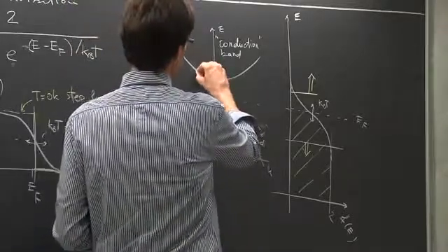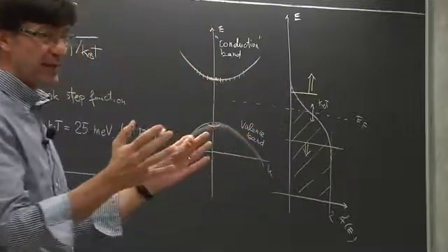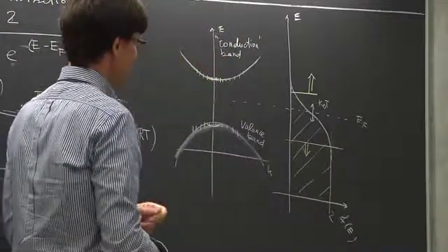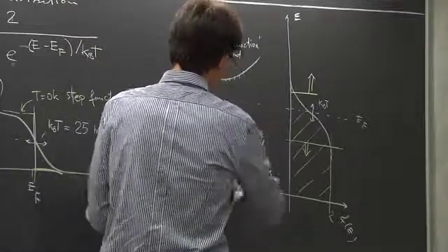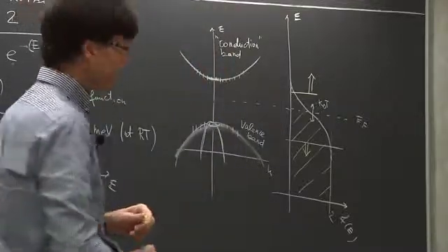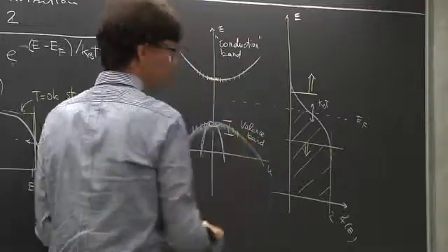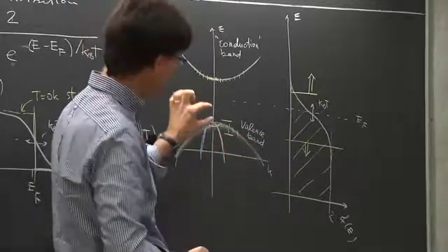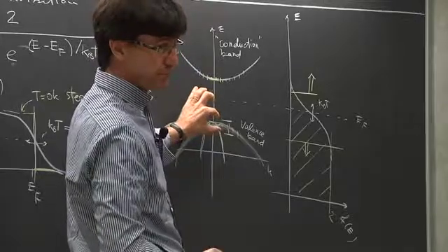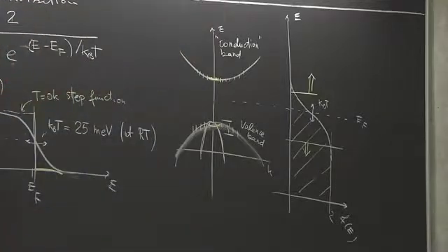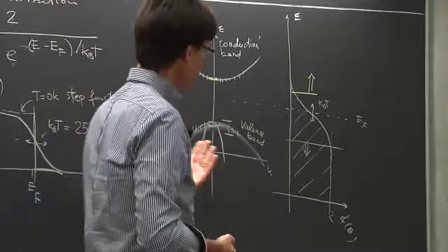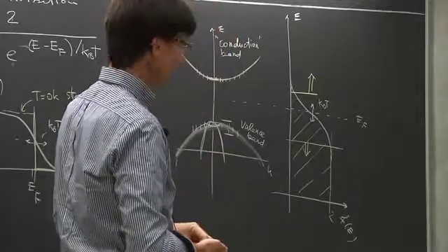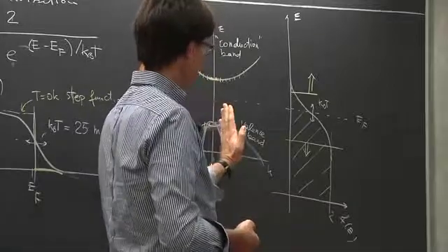Remember that the way we counted the states was assuming a uniform distribution in k-space. You might remember the discussion we had some time ago. So the distribution of states is uniform in k-space. But if the valence band, suppose, instead of being like this, is like this, very steep, then in an equal width of energy, if the states are equally spaced in k, there will be fewer available states in a given energy interval. So the important point to remember is that the states are equally spaced in k-space, but if I now look at the distribution of states along the energy variable, it's the slope of the bands that determines how many states I have.